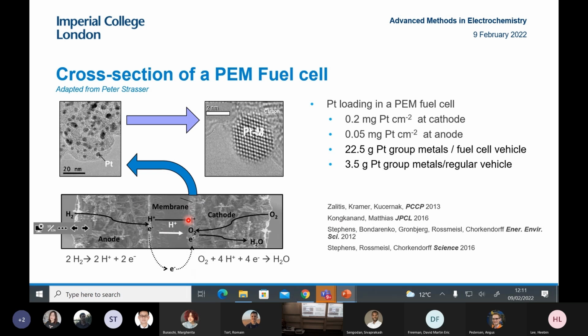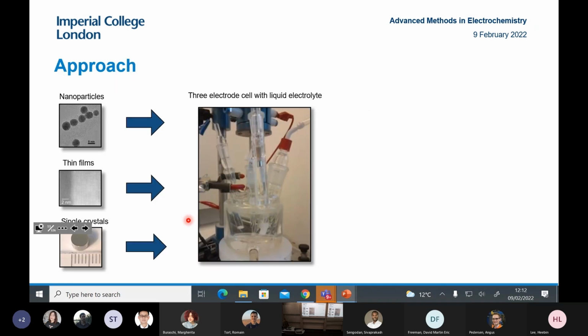So ideally, and maybe this is something we'll do in the future, we'd be doing all our measurements in an actual fuel cell and being able to relate them to first principles calculations, but it's not actually that easy to do. So usually we look at more model surfaces, which I find are easier to relate to theoretical calculations. We look at well-defined nanoparticles, well-defined thin films, and even well-defined single crystals. In this case it's a platinum single crystal, 5 millimeters in diameter. It's been annealed to expose one surface orientation.